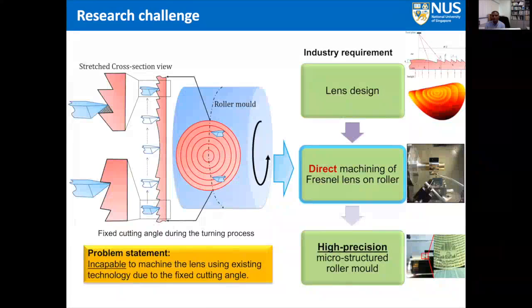So in this case, if you notice, you will see that when the cutting tool is moving in, there are some cutting edges which are very difficult to machine, especially this dark patch here. Therefore, what we need to do is make very small adjustments to the cutting tool, so that the angle of the cutting tool can penetrate into those zones for cutting the material. Okay, so we mount devices on top of the existing C or B axis in order to make these fine adjustments, and that is done with the help of a goniometer. So we mount a goniometer on top of the B or C axis and then adjust the cutting tool so that the dark zone here can also be machined by varying the tool angle.